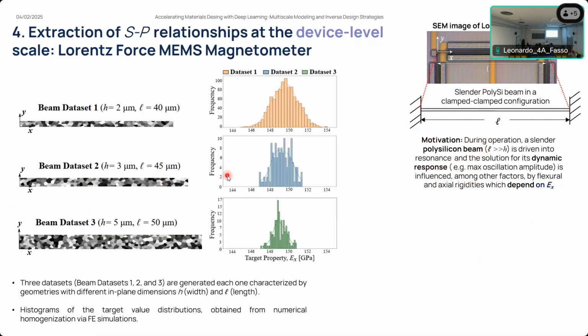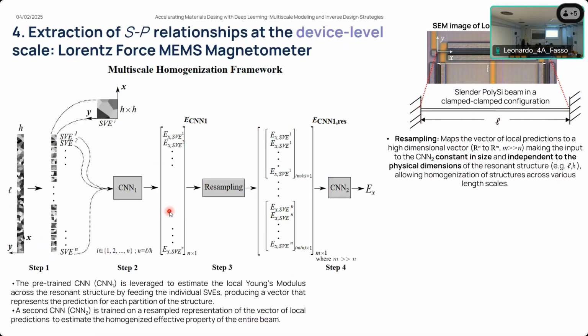So, in order to reproduce this scenario and take it to our data-driven framework, again, 3 new data sets are generated featuring different geometries of beams with different in-plane dimensions in terms of their width and length, and their target values are computed again via finite element simulation. Then we propose a multiscale homogenization framework where we can take the beam structure, and in the first step, we divide this beam structure into a series of subregions. Each of these subregions we can regard as a stochastic volume element, and therefore we can use the pre-trained CNN, the one that I presented in the previous slide, to produce local prediction of the homogenized Young modulus across the resonant structure.